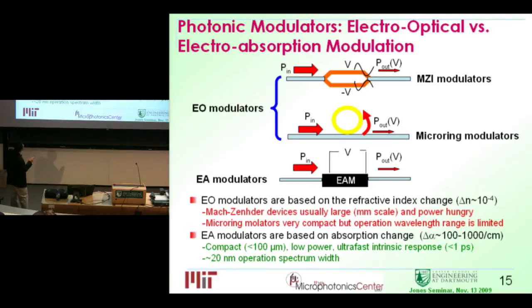A more compact version of this phase modulator is a ring. Basically, by controlling the index of the ring, you can control the coupling and decoupling of light from the waveguide to the ring and achieve modulation. But the problem is that this is a resonant device, so it only works over a very narrow wavelength range. While an electro-absorption modulator changes the absorption coefficient of a material under an electric field, so you can turn the material from transparent to opaque by applying a bias here. So it's a very convenient, very straightforward device.